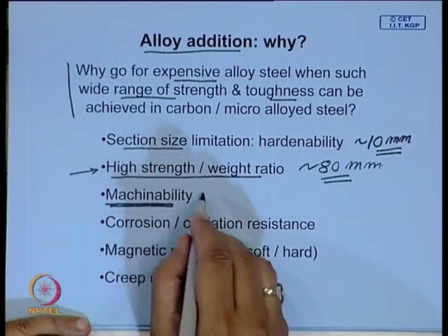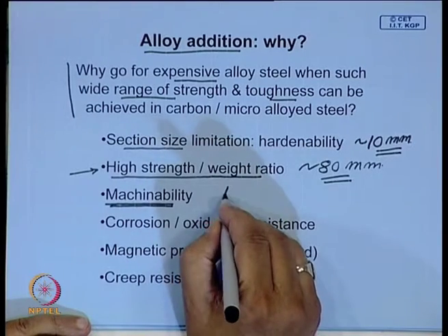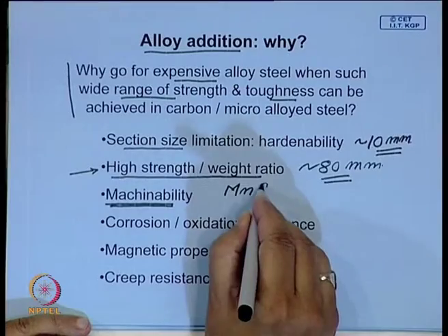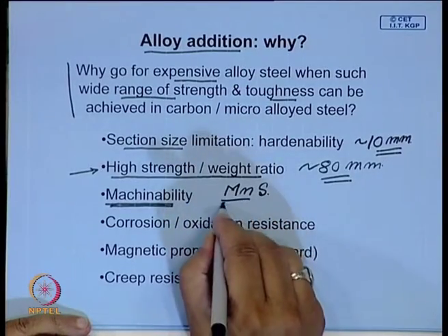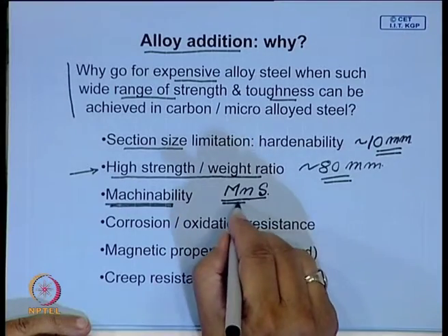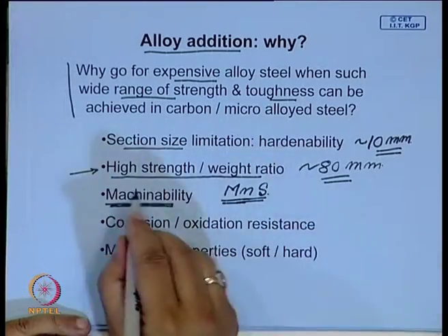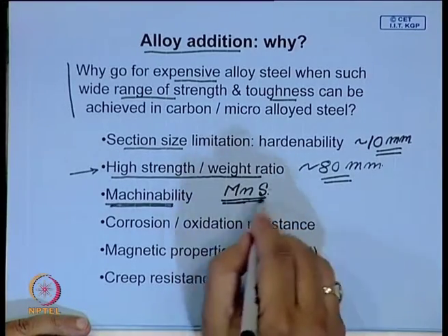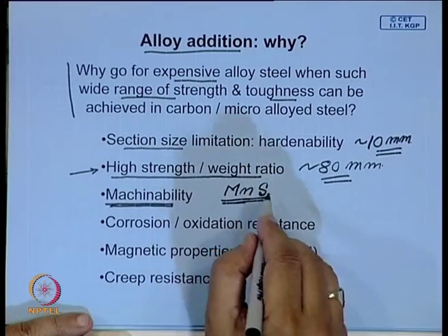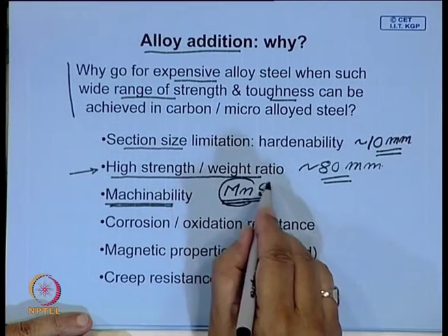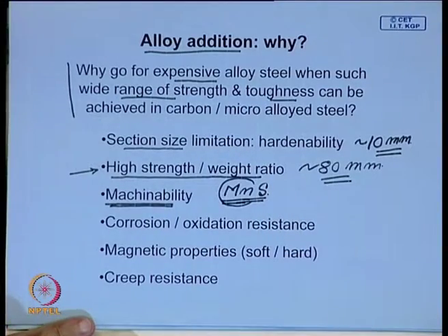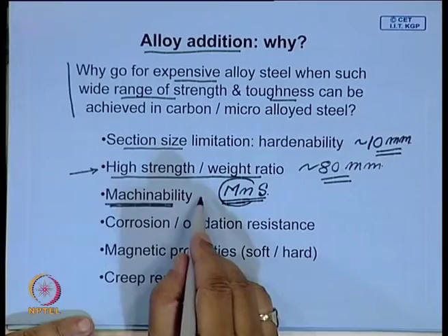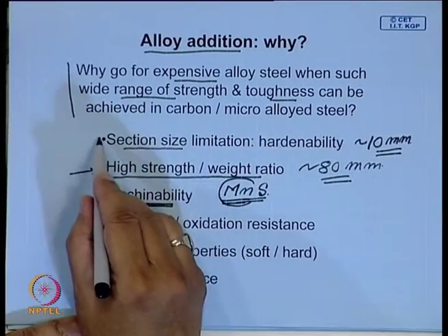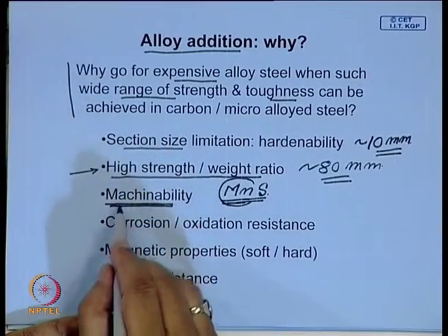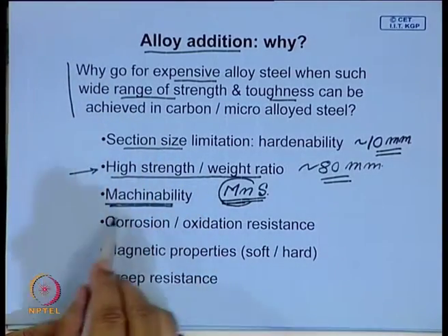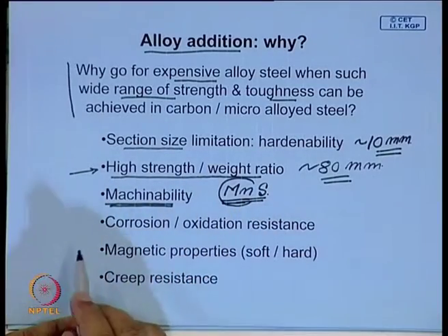So there machinability is improved by adding some inclusions. To take care of sulfur, we add manganese and you form manganese sulphide inclusions. In fact, for machinable steel, sulfur is added intentionally and you add a little more manganese to take care of it, and the presence of these manganese sulphide inclusions gives the steel good machinability. So that means, not only hardenability limitation, but also to give certain very specific properties, you need to add some alloy elements.